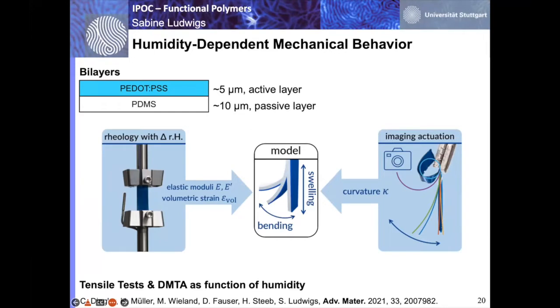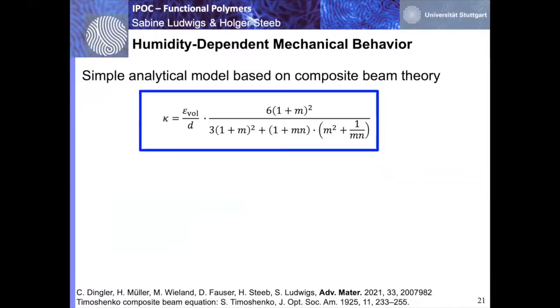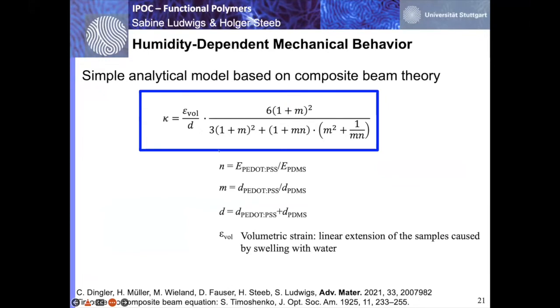As you will see, that's a model of Timoshenko. And with the model, by using the parameters from rheology, we can predict the bending behavior, and we can compare that with the real actuation images, which we take during the experiment of the actuators in wet atmosphere. So this simple analytical model is based on a composite beam theory, which is coming from Timoshenko. Just quickly going through the equation.